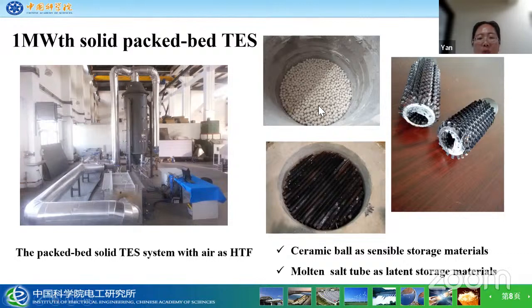We used ceramic balls as the principal storage material, and high temperature air as heat transfer fluid. The air temperature is about 800 degrees, and in order to stabilize the temperature of the air outlet during the discharge process, we also developed a new kind of latent thermal storage material, which is a molten salt tube. That is the tube. We put the molten salt into the tube and combined this tube with the ceramic balls. We did more experiments and saw that the air temperature can be stabilized during the discharge.